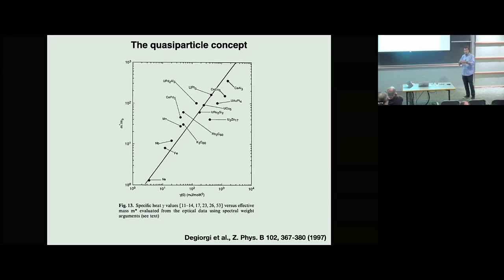Angle-resolved photoemission could measure, let's say, velocities around different parts of the Fermi surface, and these might be related to each other. But we can have things like susceptibility and compressibility, which even at the level of Fermi-liquid theory aren't sensitive to electron-phonon interactions, but become sensitive to electron-electron interactions. There's also cyclotron resonance experiments, which, as I'll discuss more, give very, very different considerations.